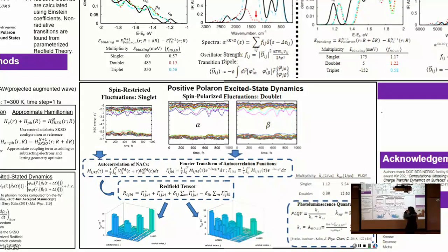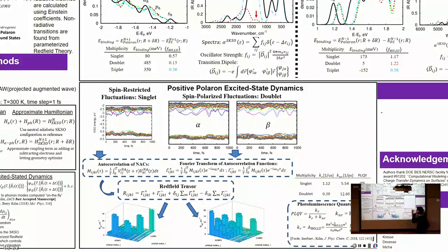So to do our dynamics, we actually have to couple electronic and nuclear degrees of freedom. We do that using adiabatic molecular dynamics. And these figures show the energy fluctuations of the Kohn-Sham orbitals along the trajectory. These fluctuations correspond to coupling to phonon modes along the trajectory. And if you've taken enough statistical mechanics, you probably have it burned into your mind that fluctuations lead to dissipation. So that's why we start with showing energy fluctuations of our models.